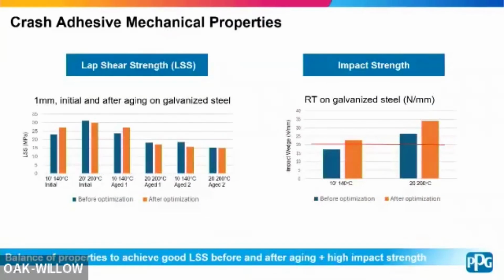On the mechanical property side, I'm just showing some representative data here for our crash adhesive. We also have a high crash that has even higher strength performance, but focusing on the lap shear strength first. So this is looking at a 1 millimeter bead, making sure we have really good lap shear strengths before and after exposure and within our full cure window. It's a little bit of a complicated graph, but essentially we're just showing before and after some optimization. First, initially at 10-minute 140C cure times, and then at this kind of more overbake condition at 200C, 20 minutes.